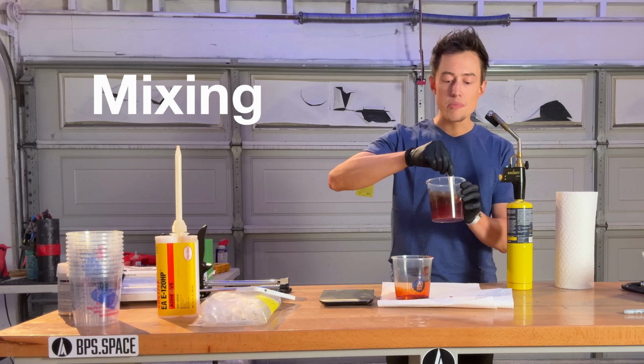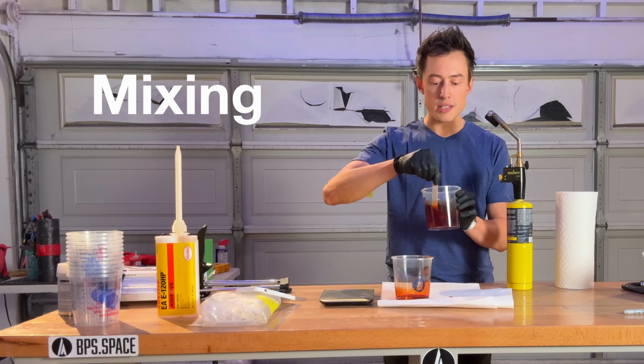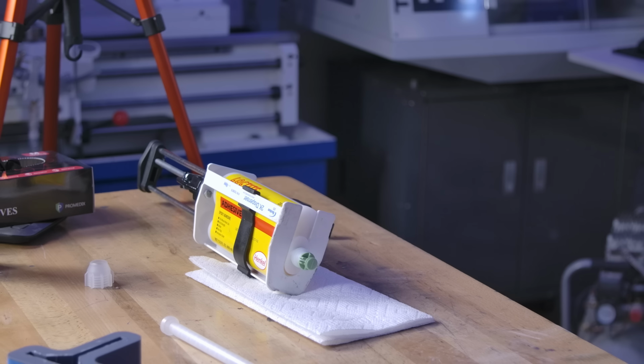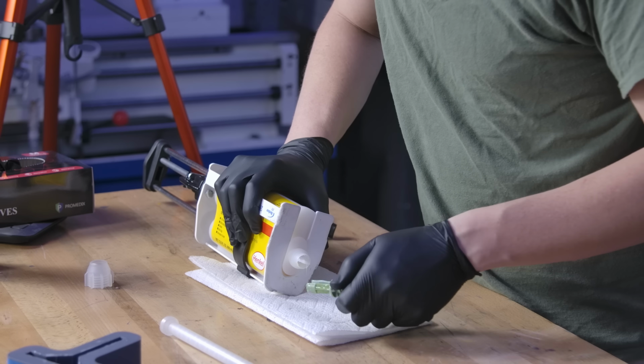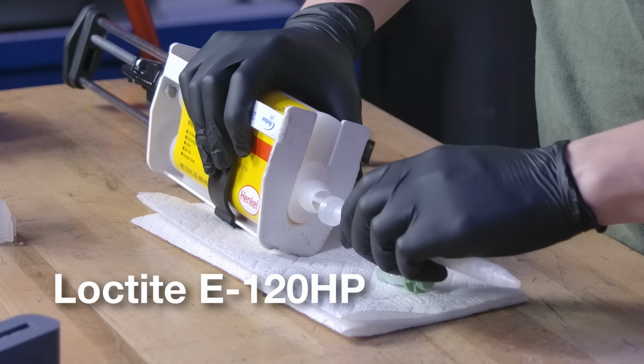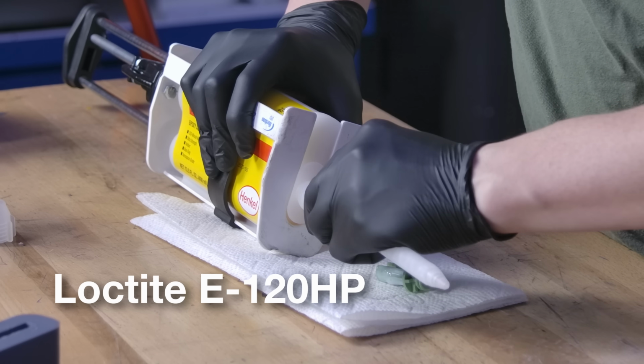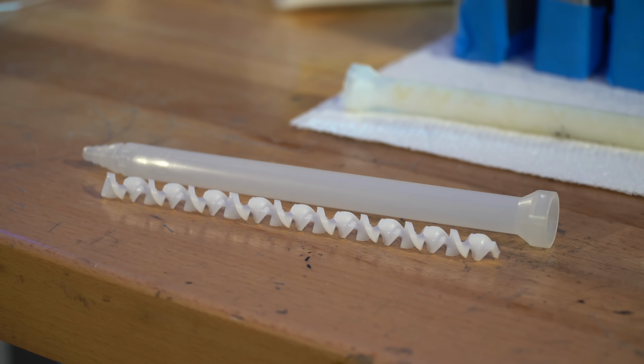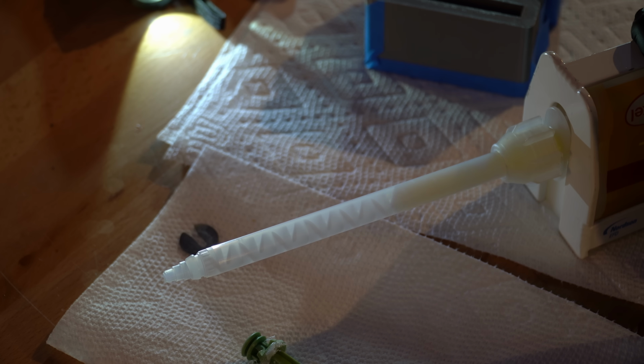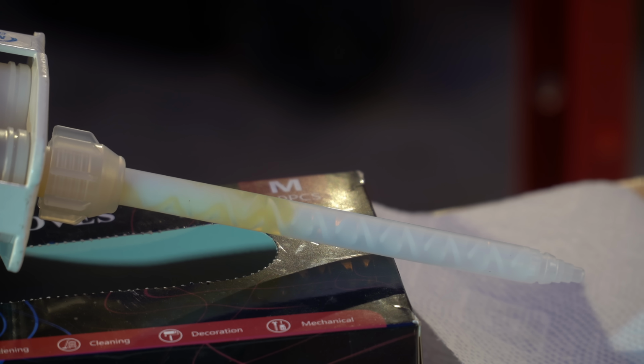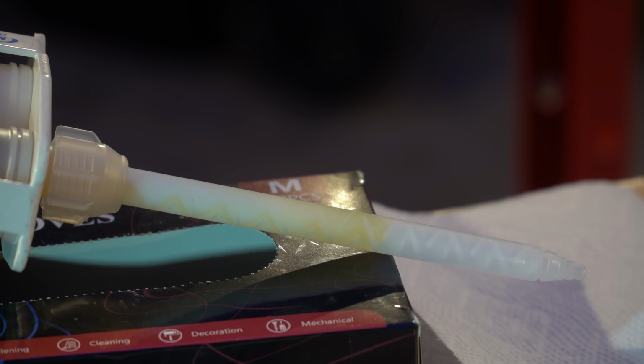How well do you need to mix these two things together for the epoxy to cure fully? The epoxy I'm using here, Loctite E120HP, comes with mix nozzles that mix it for me. But are these really enough? The nozzle swishes these two liquids back and forth using baffles inside. Mixing it this way reduces bubbles, and it means you should be able to apply it directly to the parts.